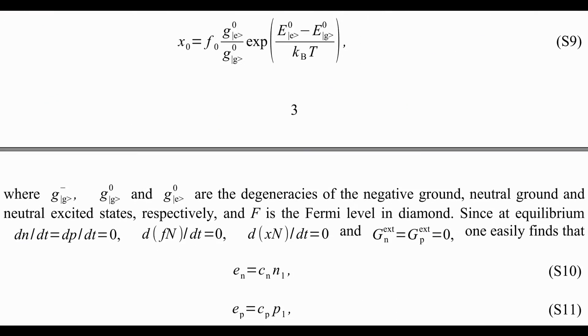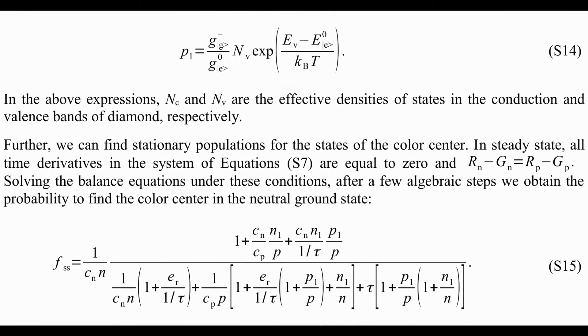Since the physics behind the electroluminescence process was not known, it was not clear to what extent the photon emission rate can be increased, and whether color centers in diamond can compete with electrically-pumped epitaxial quantum dots and other single photon sources. In this work, we reveal the electroluminescence mechanism and present for the first time the theoretical framework to study single photon emission from color centers in diamond under electrical pumping. Moreover, we demonstrate that it is possible to design an ultra-bright electrically-driven single photon source based on color centers in diamond, with an emission rate as high as 10 to the power of 9 counts per second at temperatures above room temperature.